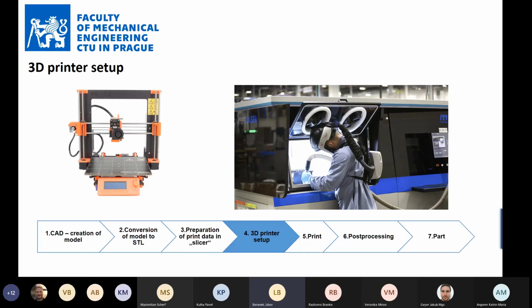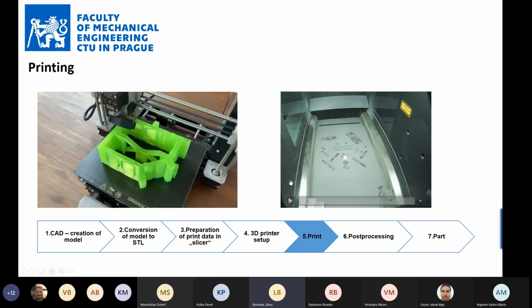So you again have to keep some rules when you are handling powder, when you are sieving the powder. Before or after every print, you have to take the powder in some kind of container with a protective atmosphere. You have to put it into the sieving machine, which separates the particles with incorrect geometry from the powder so you can reuse it. Even this sieving machine has to have a protective atmosphere, and this process may take 3-4 hours just to prepare the next batch. So this is something you have to consider. Then the print itself for the DMLS technology is, I would say, very simple.